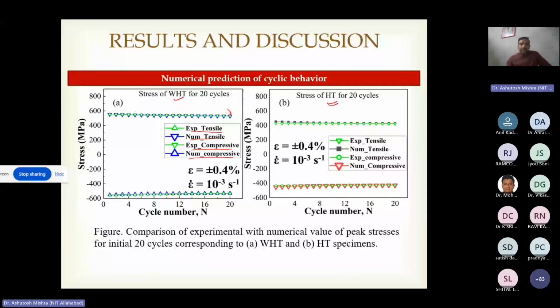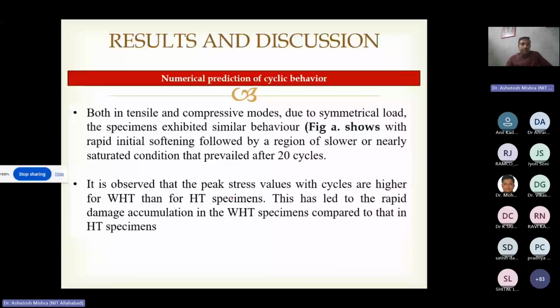Now, in both tensile and compressive modes, due to symmetrical load, the specimen exhibited similar behavior. The figure shows rapid initial softening followed by a region of slower or nearly saturated conditions that prevailed after 20 cycles. It is observed that peak stress values with cycles are higher for WHT than for HT specimens. This has led to rapid damage accumulation in WHT compared to HT.